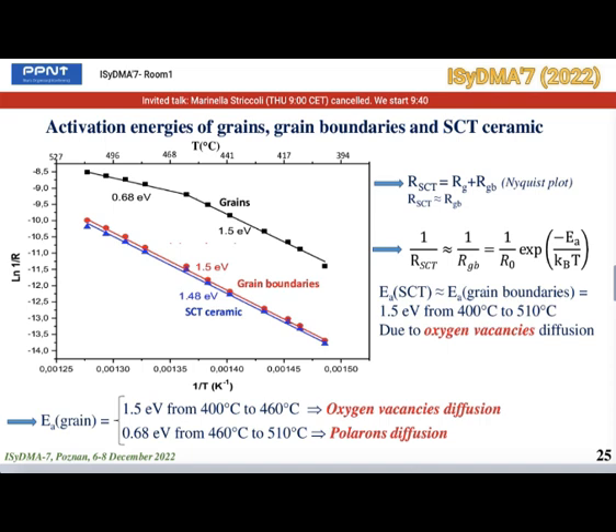We show here the evolutions of the inverse of resistances of grains, grain boundaries, and SCT ceramic. The resistance of the ceramic is obtained by adding the resistances of grains and grain boundaries. These evolutions as a function of the inverse of temperature are of Arrhenius type. We notice that the resistance of the ceramic is very close to that of the grain boundaries. Therefore, the activation energy of the ceramic and that of the grain boundaries are close.